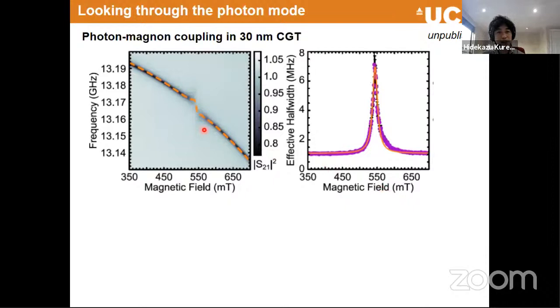This is the measurement when we sweep, a 2D plot as a function of frequency and magnetic field. You can see this line represents the resonance frequency shift when you apply the magnetic field, simply because of the superconductive nature. And you can notice that there is a faint region in the middle. This is the region where the magnon mode overlaps with this resonator mode. Then we measure an individual peak in the magnetic field cut.